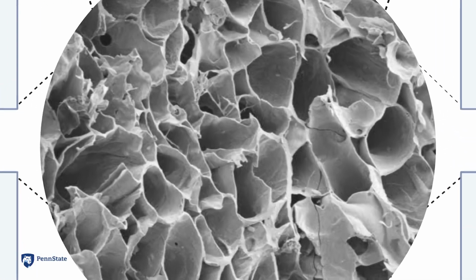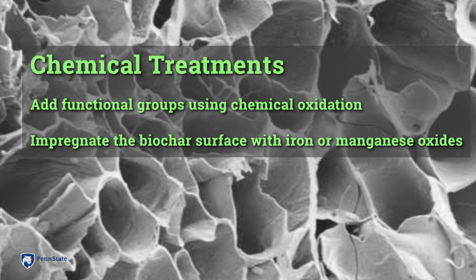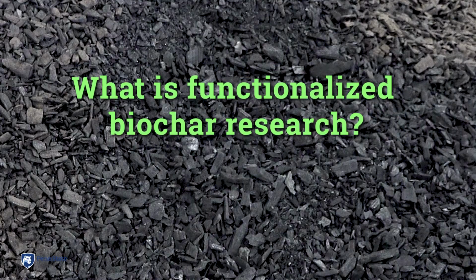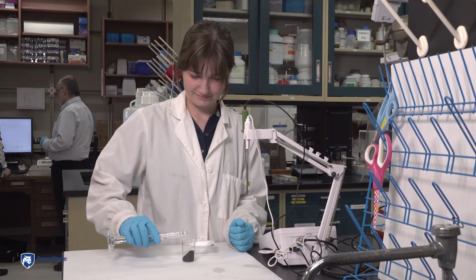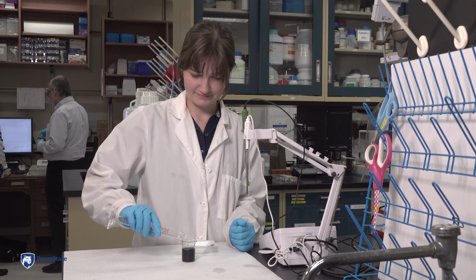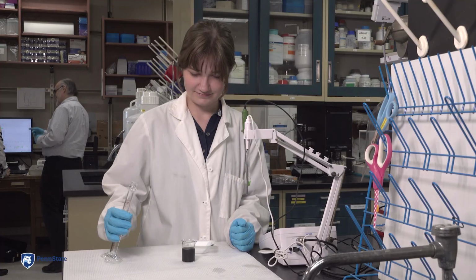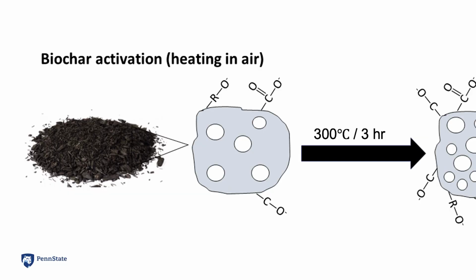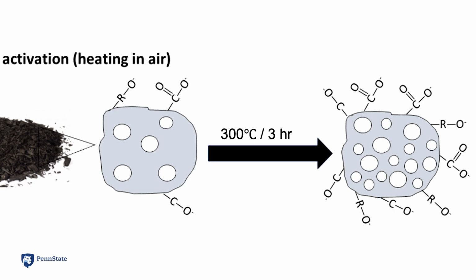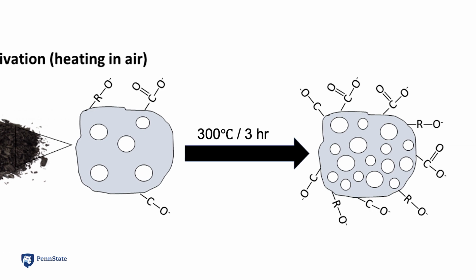Scientists have developed several techniques to improve this binding of lead by chemically treating the biochar. We can add functional groups using chemical oxidation or impregnate the biochar surface with iron or manganese oxides to enhance lead sorption. At the Soil Research Cluster Lab at Penn State, we are demonstrating the effectiveness of using just heat and oxygen to modify biochar. Biochar is produced in a low oxygen or no oxygen environment, so by heating it in the presence of oxygen, we are able to add functional groups to the surface of the biochar, therefore increasing its sorption of lead.